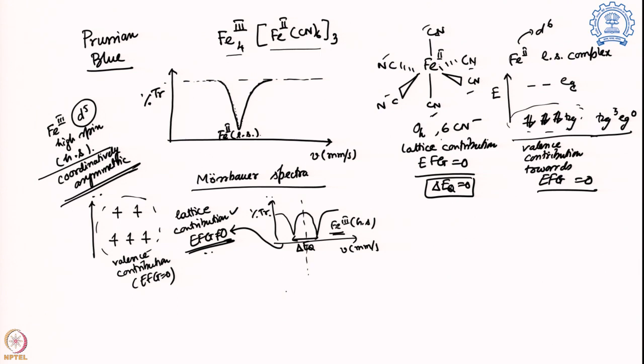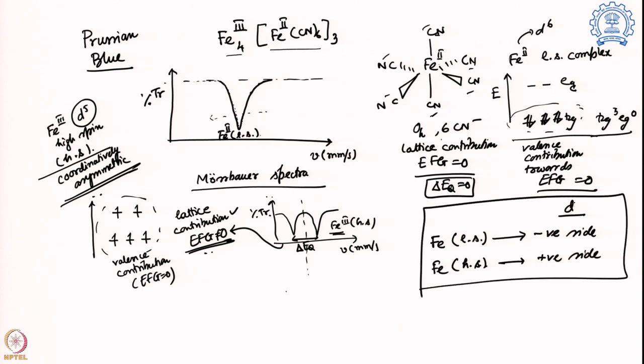And over here there are two different factors. One is, it is iron plus 3, and as you know, iron plus 3 should go, to be honest, on the left hand side. But over here there is another difference, it is high spin versus low spin. And over here I say the low spin systems of iron generally go to the more negative side of the delta value compared to iron in a high spin state, which goes to the more positive side. Now the question is, why does it happen? That we will cover a little bit later, but for now we found that this high spin system will be on the positive side and the low spin system will be on the negative side.